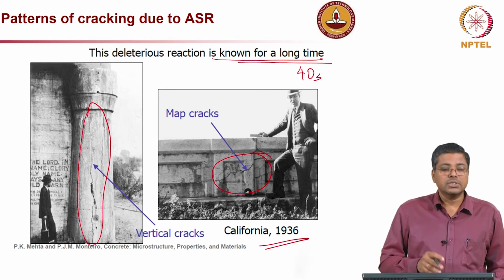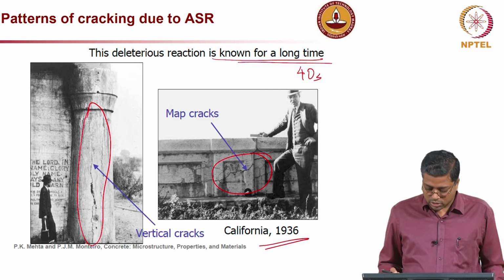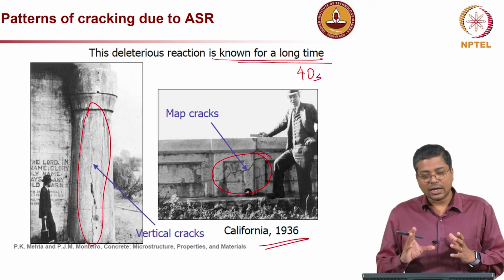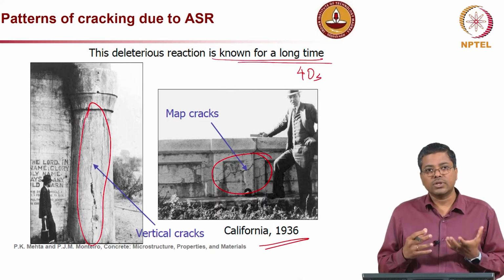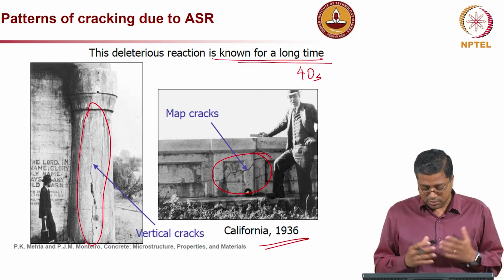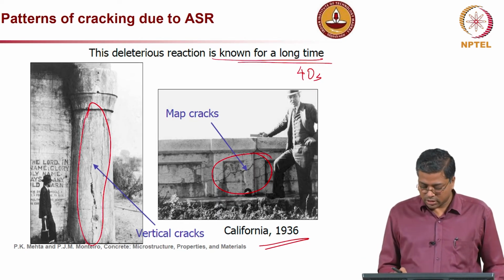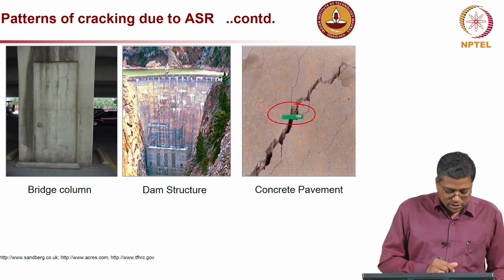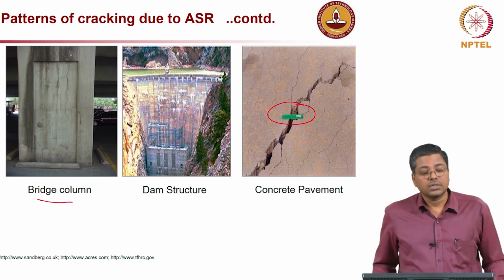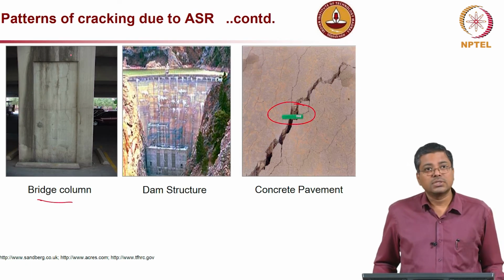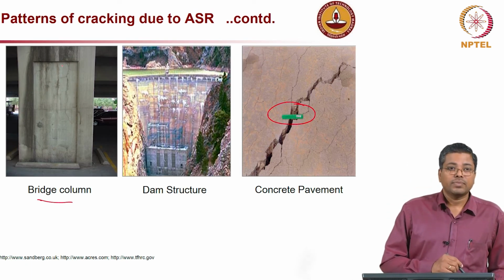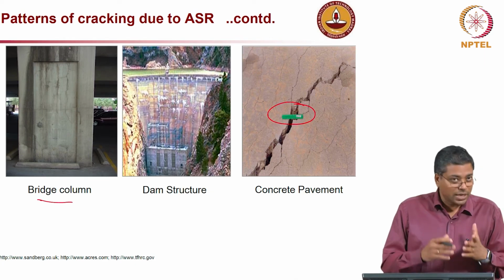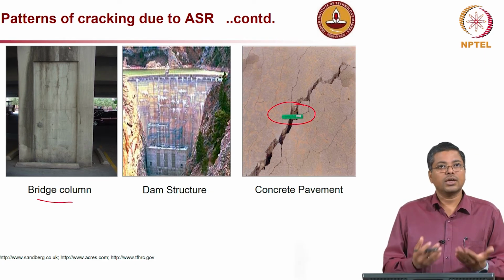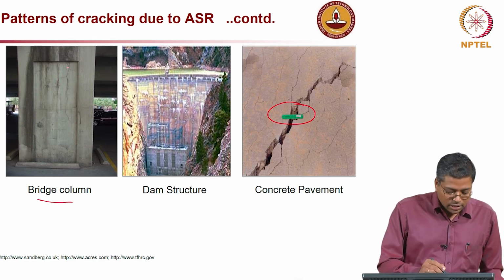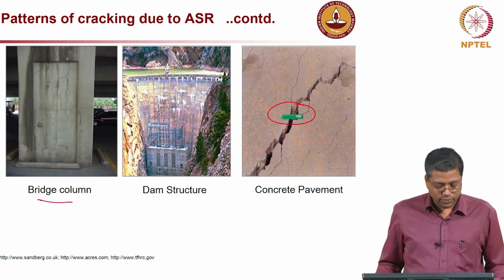If you look close up, you will see that there are a lot of map cracks on this column also. Essentially, what it is telling is the cracking is happening because of the stress generated from within the concrete system, and not because of corrosion or any other mechanisms. In this picture, on the left side you have a bridge column, and I have seen this bridge column. On the other side of this same bridge, you do not have any cracking, even though it is the same concrete. On one side you have significant cracking, and on the other side you do not. The main reason is on this side, the side which is visible to you.